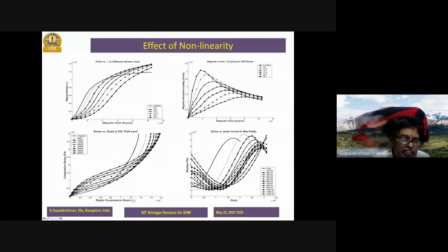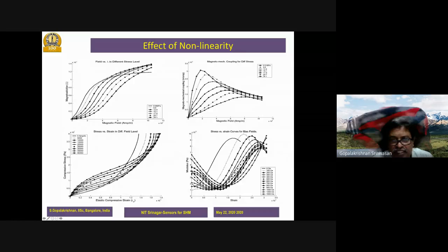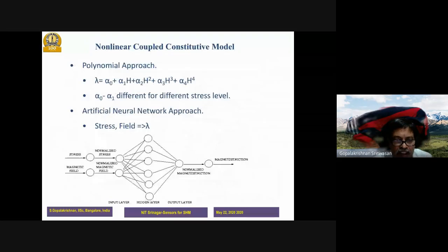Even the magnetostriction changes with different stress levels, and manufacturers only give you data for certain conditions. If you want to design a sensor, we need to have a robust method to estimate it. So what we did here is we tried a couple of numerical approaches. We actually assumed the magnetostriction as a polynomial function of magnetic field, and these constants were determined.